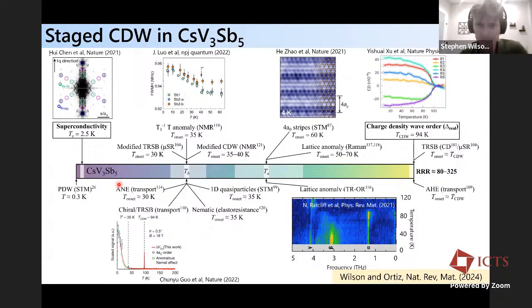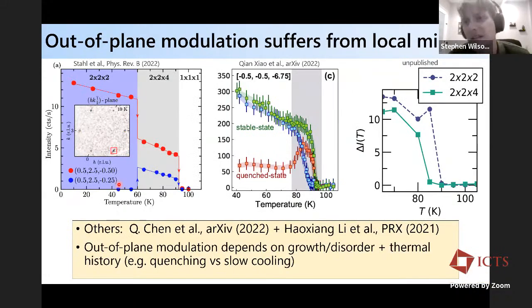Okay, so it has this complicated structure, and it also seems to have this more complicated starting phase. And so one of the oddities is that the charge density wave for the cesium system seems to be marked by metastability, meaning there are different studies, I'm highlighting a few here, where if you quench the system through the charge density wave state or slowly cool it, then you suppress or modify the relative intensity of the 2x2x4 superstructure relative to the 2x2x2. Okay.